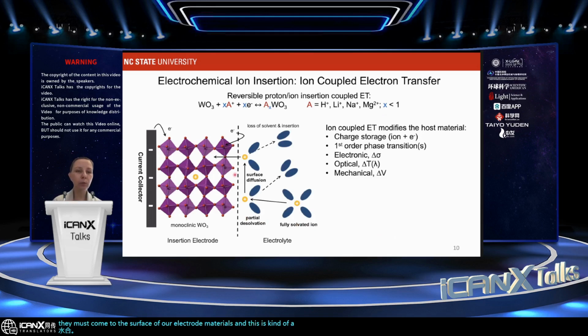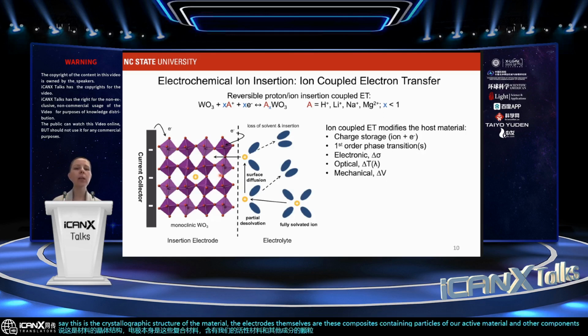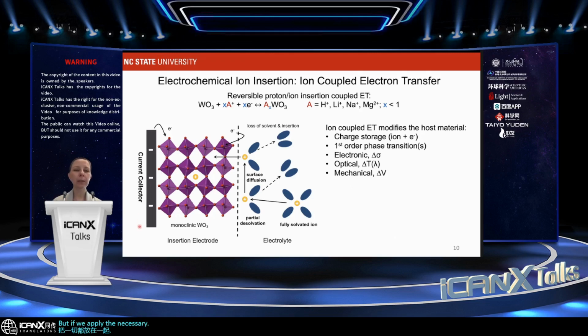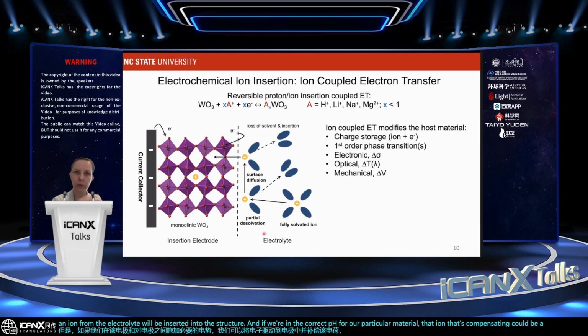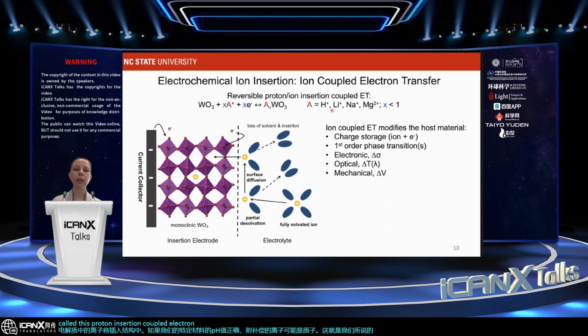And this is a very zoomed in perspective where we say this is the crystallographic structure of the material. The electrodes themselves are composites containing particles of our active material and other components to keep everything together. But if we apply the necessary potential between this electrode and a counter electrode, we can drive electrons into the electrode, and to compensate for that charge, an ion from the electrolyte will be inserted into the structure. And if we're in the correct pH for our particular material, that compensating ion could be a proton. And that's what we call proton insertion coupled electron transfer. It could also be other kinds of cations. In the case of tungsten, you could have lithium, sodium, even magnesium.